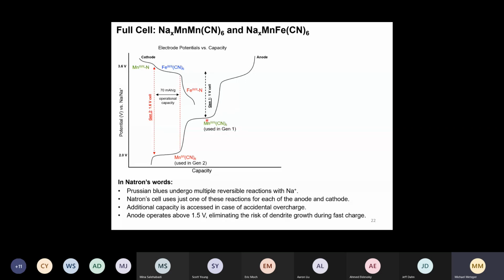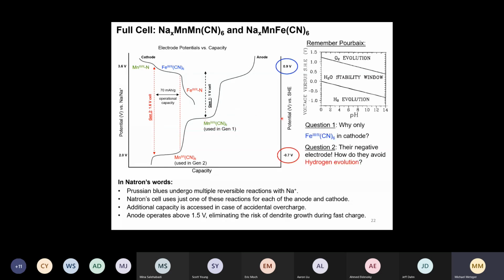Now, why didn't they do this all the way from the start? And the reason is we can plot these potentials also versus the standard hydrogen electrode, which is very useful because the Pourbaix diagrams are typically written in that way, that you report the voltages versus the standard hydrogen electrode. So this is a simple conversion from voltage versus sodium. You can convert to voltage versus lithium, or you can convert to voltage versus any reference electrode, really.